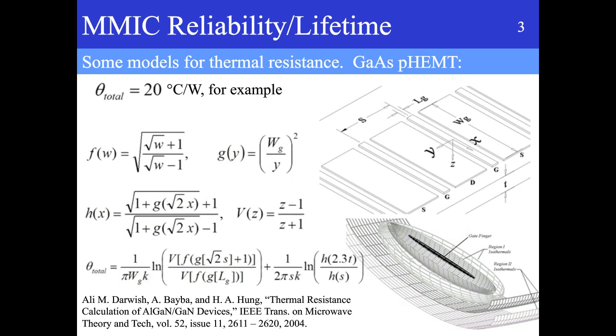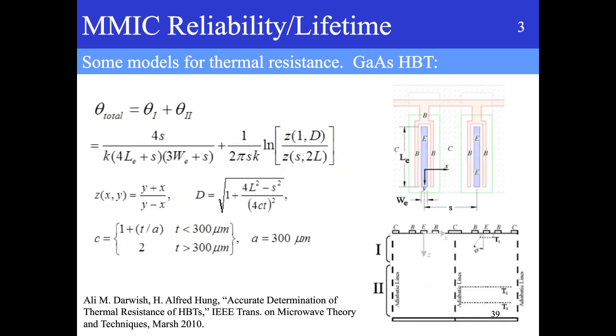For example, here I'm showing equations for gallium arsenide, and it helps you by taking into account the gate spacing, the gate length, gate width, and so on, to plug it into these equations and give you what's the thermal resistance. And for example, let's say the thermal resistance is 20 degrees C per watt. That means for every watt of dissipation, the junction temperature will go up by 20 degrees. And so the more efficient you make an amplifier, the more life it will have.